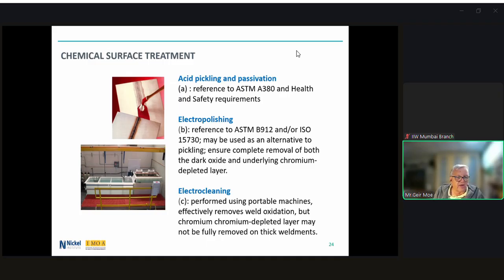Electrocleaning is a kind of variation of electropolishing. It's performed using portable machines that effectively remove heat tint, but the chromium depleted layer may not be fully removed on thick weldments. It is dependent on the thickness of the heat tint and the application time.